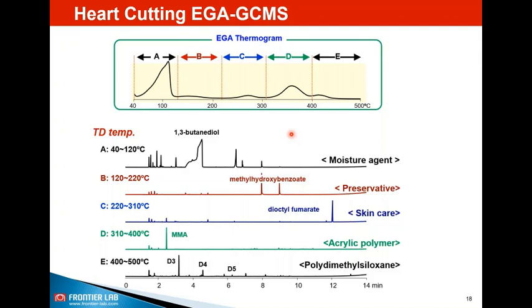Then it is better to start with EGA. Otherwise, we have a rule of thumb. Any polymer you want to do, 550 or 600 can be used for flash pyrolysis. Similarly, for thermal desorption, it can be 100 to 300. So this is a general recommendation, but this may have to be varied a bit depending upon the type of sample and the analysis objective.